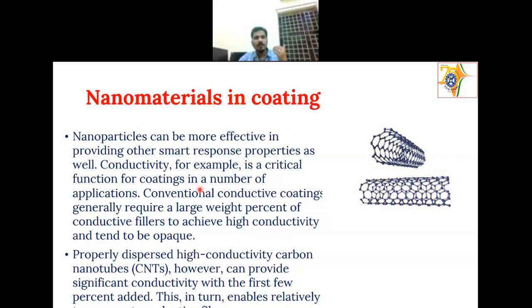So you can add some kind of fillers to reduce the amount of zinc in the coating, but at the same time you cannot add just any kind of filler, because the filler should be conductive. The filler should be conductive to maintain the electrical connectivity between each zinc particle, and from the zinc particle to the iron particle. So carbon nanotube finds a good application in this formulation. So various things are available now.